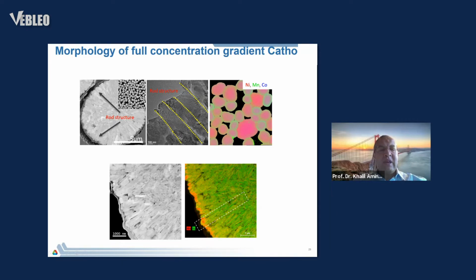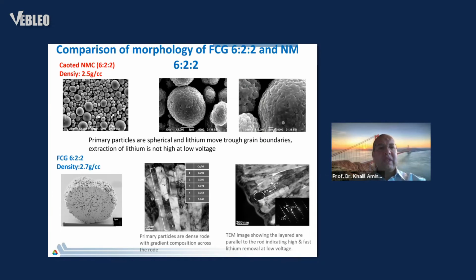So we did a comparative study where we took a coated NMC that is used in automotive today, and then we made an average composition similar, FCG we call 622, but keep in mind that the nickel is higher in the bulk and is lower at the surface. So the first thing we find is the density of the material is much higher than the commercial material used for electric vehicles. Density is very important because you can pack more active material in the electrode, and that can lead to more energy increase. The reason why the density is higher is because the primary particles are rods and very dense.